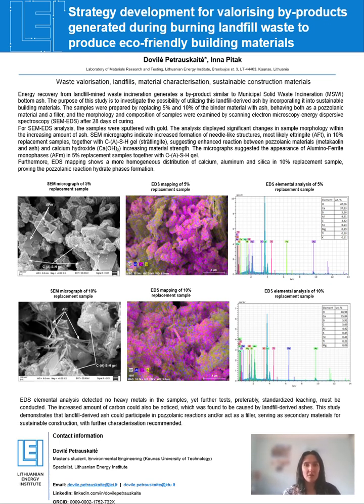So the coexistence of AFm and AFt phases together with a C-S-H gel basically demonstrates that the landfill-derived ash is not really inert, and it participates in hydration reactions. So this pozzolanic behavior could improve strength and durability while also reducing the amount of conventional binder required.